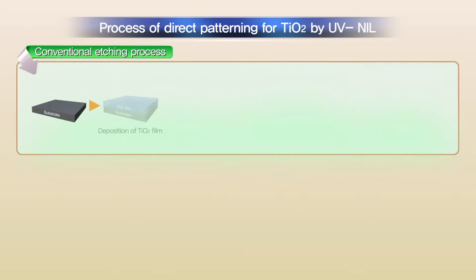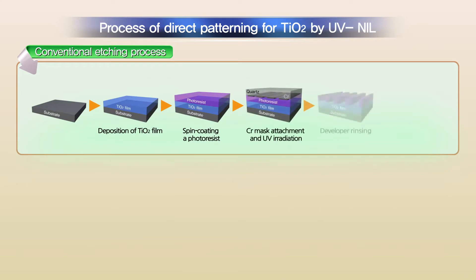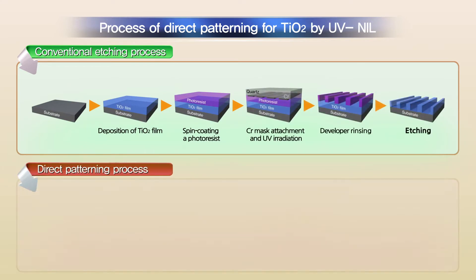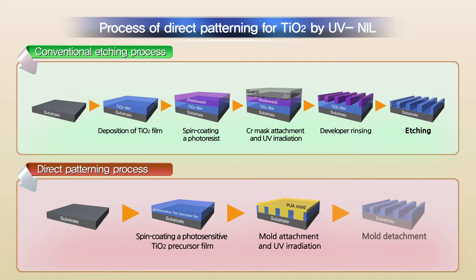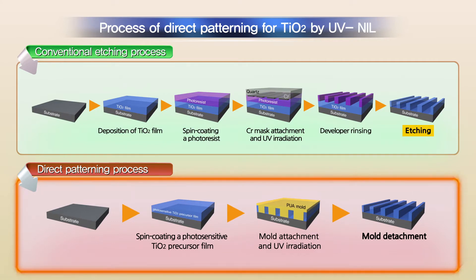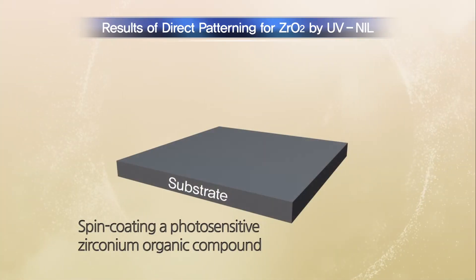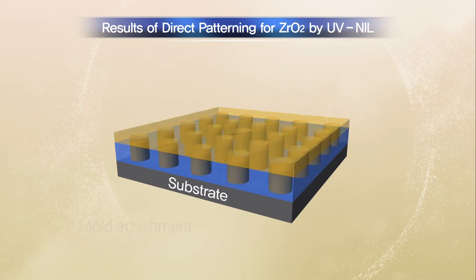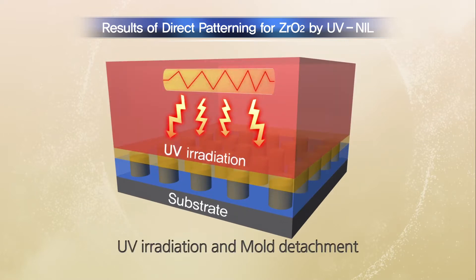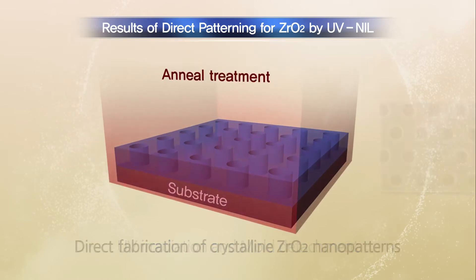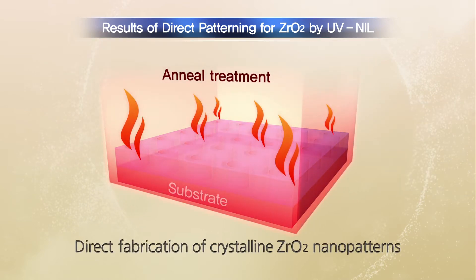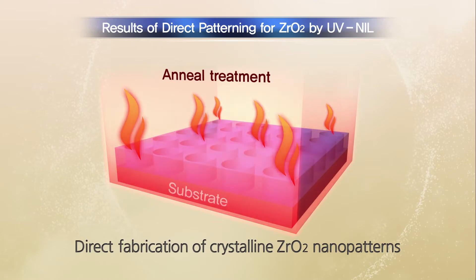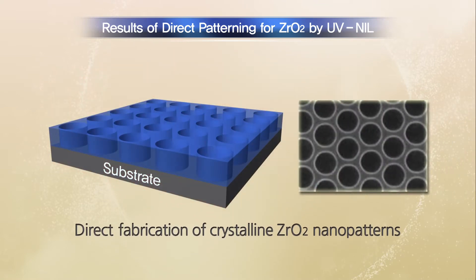Metal Oxide Direct Nano Imprint Lithography is a process capable of manufacturing nanopatterns of metal oxide without the high-cost lithography indispensable for existing nanopatterning processes. After applying pressure to the nano mold, organic and inorganic materials containing metal oxides harden the nano mold by radiating ultraviolet rays and are then separated. After removing organic materials through heat treatment at 300 degrees Celsius, metal oxide nanopatterns are formed.